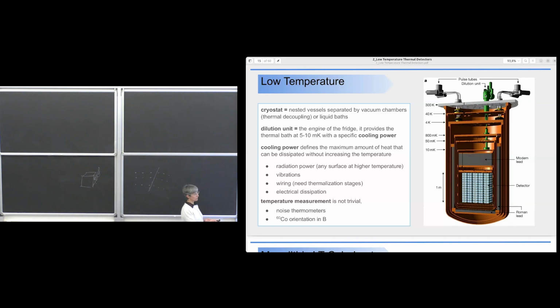And we measured the flux of gamma rays when the cryostat was warm. And then you measure it when you have cooled it down, and you have a prediction of the flux. You can correlate the flux of photons that you measure with the temperature, that means with the orientation of the spin in the cobalt-60. However, this technique cannot be used when you have a detector that you really want to operate, because this is radioactive. So I cannot place at the bottom of the Cuore array a cobalt-60 source.